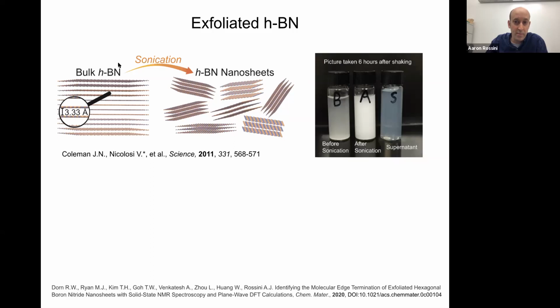So the way we made the samples for this study is we took bulk hexagonal boron nitride, which you can just buy from any commercial chemical vendor. You just placed it in a liquid. You can use organic solvents, or in our case, we just use water. If you take your boron nitride and you put it in water and then you sonicate it, you'll actually partially exfoliate the sheets into smaller nano sheets.